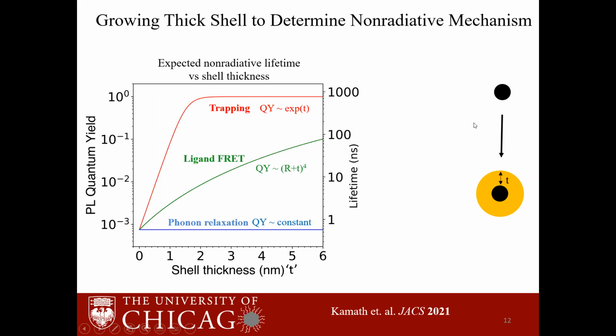And here I have a graph of the calculated PL quantum yields for core shell quantum dot with different shell thicknesses. And since the three mechanisms come from fundamentally different physical origins, growth of the shell has different effects on the non-radiative rates. For the first mechanism, which is surface trapping, it involves a quantum mechanical coupling between the electron or the hole wave function to the defect states on the surface. So as we grow a shell, we are introducing a quantum mechanical barrier. So we should expect the quantum yield to increase exponentially with the shell thickness.